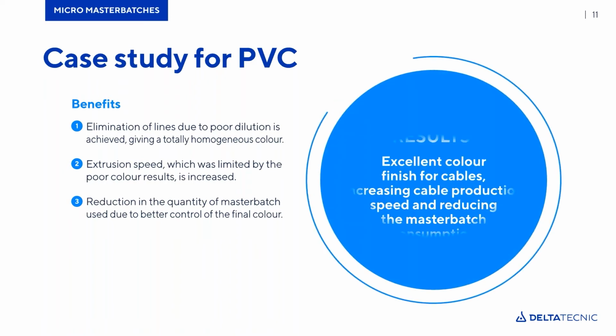And what happened is that it went very well. Immediately, the customer got control over the color. The color finish changed and was regular. They didn't face anymore the problem with these lines, this color getting lighter and then darker as before, which in the case of the automotive wire, you may appreciate in the spool at the end. You have a spool, you have high-speed production, and then you have these color fluctuations. They go up and down, they get darker and then lighter, and then you can see it in the spool, and you may face non-conformities from the side of the customer.